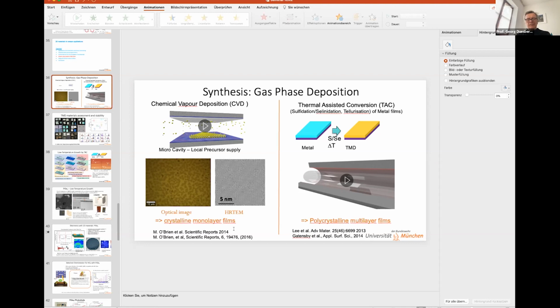The main reason why we used it is that we had, let's say, a defined source of the molybdenum trioxide precursor. Most people just mix it somewhere in the tube. They sometimes get nice growth, but since you get this precursor everywhere in your tube, you then get very varying results in the next runs. So this was a way to define the molybdenum trioxide precursor.